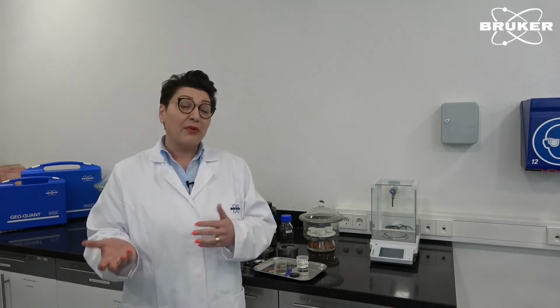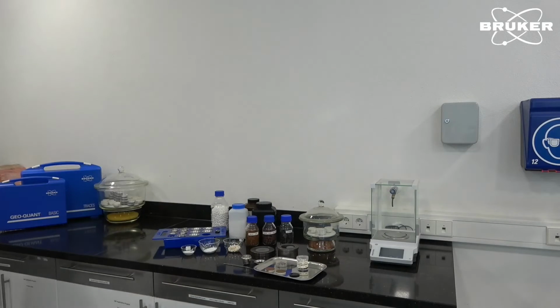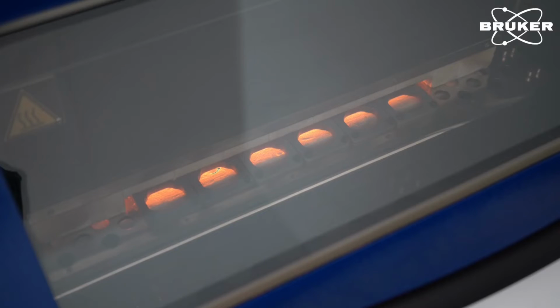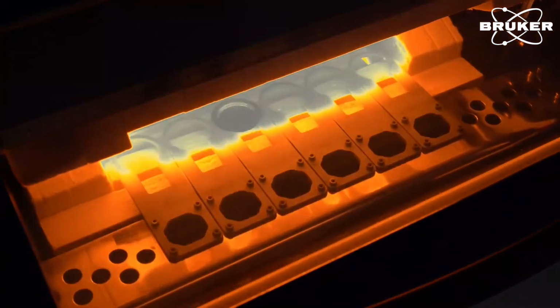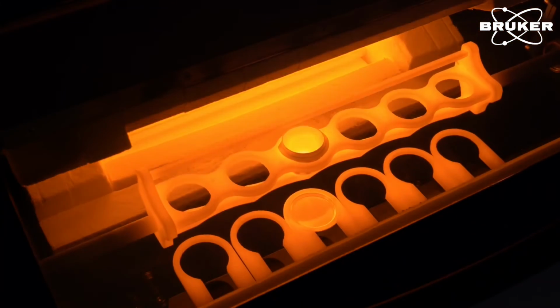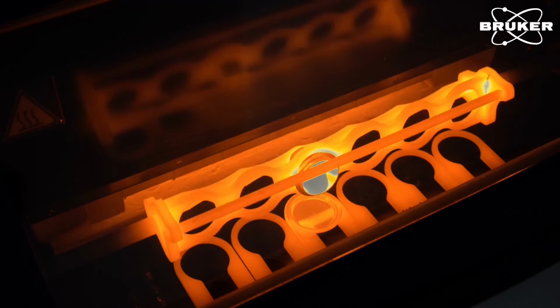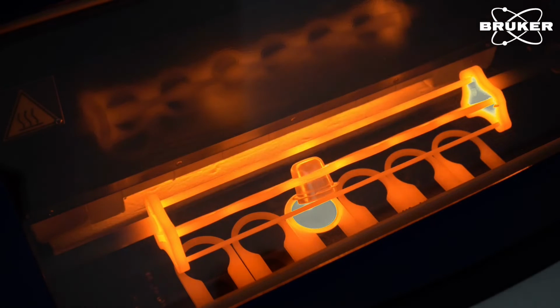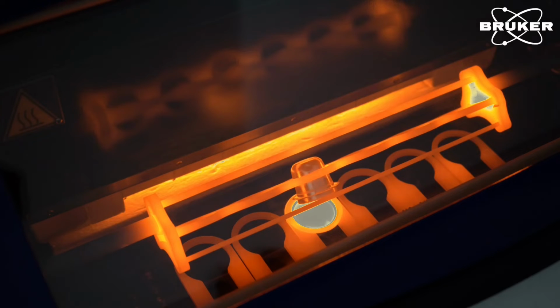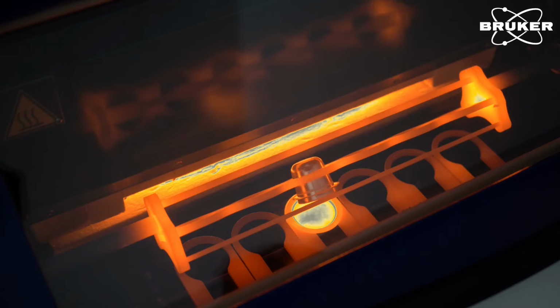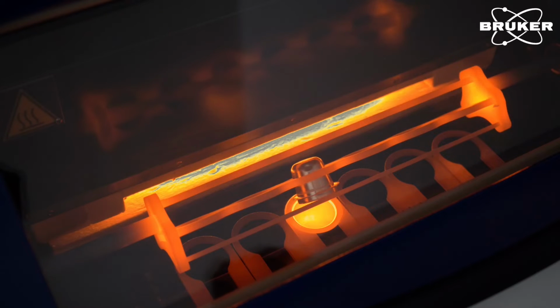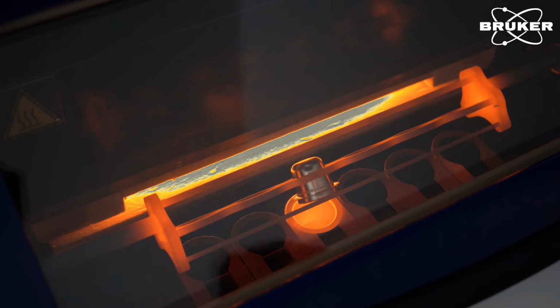To show you a little bit how the sample is casted in a fusion device, here I already started one measurement, and I will just go to the fusion machine and show you how this works. So we're just in time. Here you can see this is an electrical device with a muffle furnace. The sample was heated and also the mold was heated. And now you can see how the sample is casted into the mold. After the sample is poured, the system will cool the mold so the sample can be released manually out of the system. That's it. The fusion process is now finished.